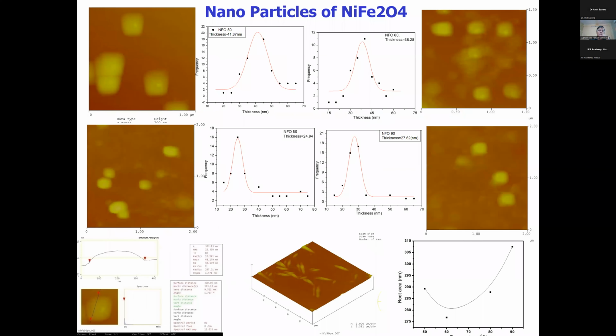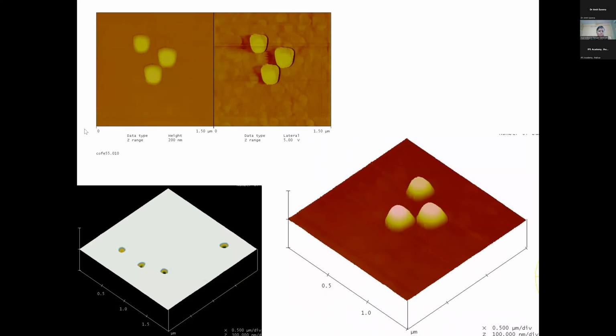So these are all very interesting papers that our collaborators have come up with. I think one of the collaborators of Neetu Bhavna has done work from Ujjain. Chemically prepared nano dots, nano wires and nano rods can be made for nickel ferrite particles. So the size dependent magnetism we want to study. If you make a nanoparticle of 10 nanometer, 20 nanometer, 100 nanometer, how does the magnetism go from bulk to nano? The beauty of this chemical co-precipitation is that you can produce all the particles of the same size and same shape. No physical method can do that. Chemistry is very interesting. So that's what we are trying to show.